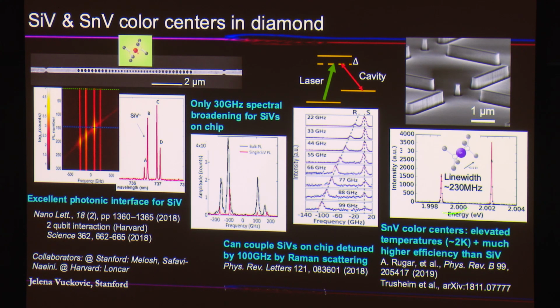And this one is exciting to us because it turns out that you can work at slightly higher temperatures. It has much larger ground state splitting, 850 gigahertz as opposed to 50 gigahertz. So you don't really have to cool it down to millikelvin temperatures to see the best results, to avoid phonon-induced decoherence between ground states. So you can work at temperatures of a few Kelvin, and it also has higher internal quantum efficiency than silicon vacancy. It's simply brighter.